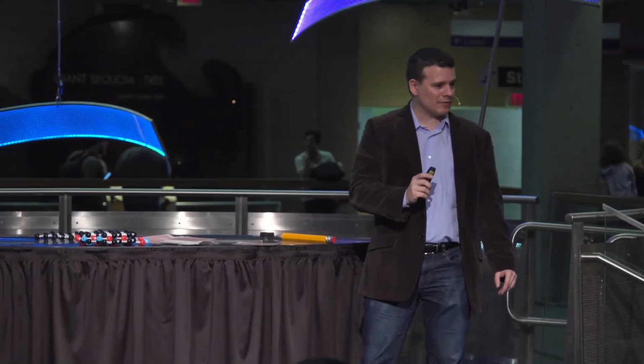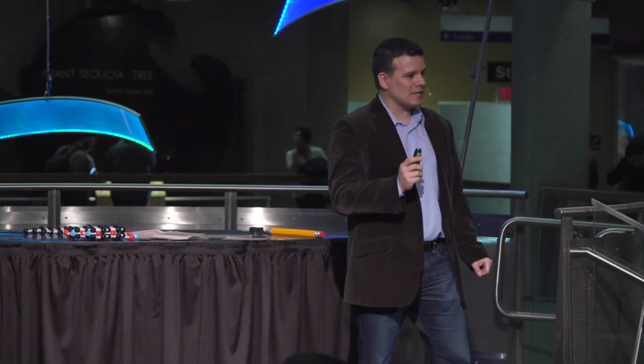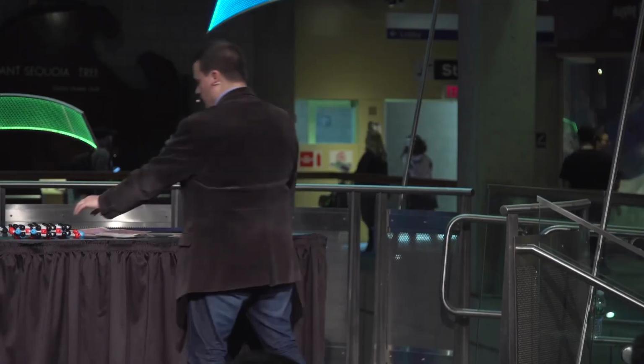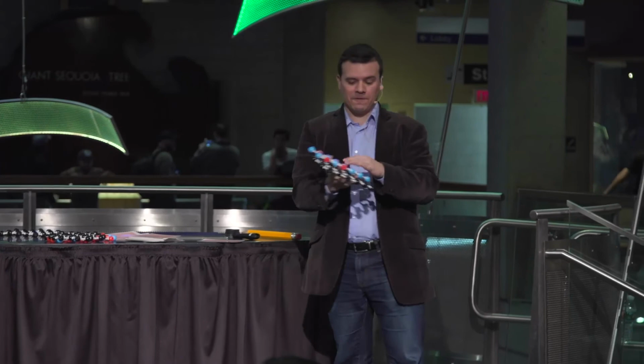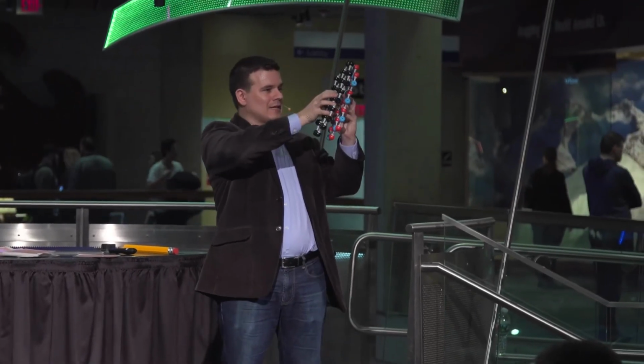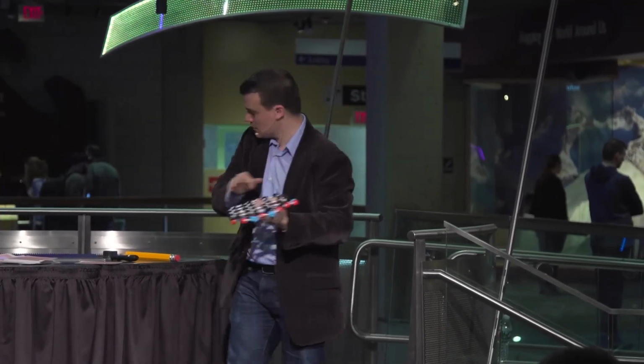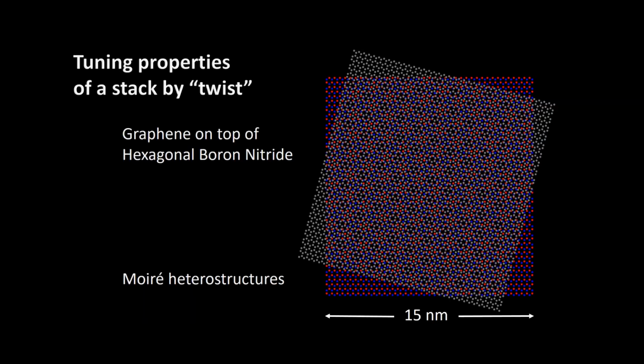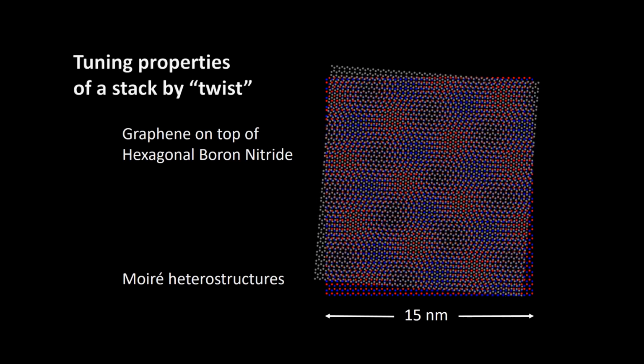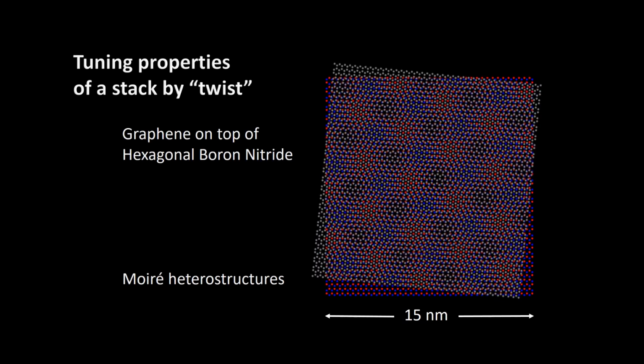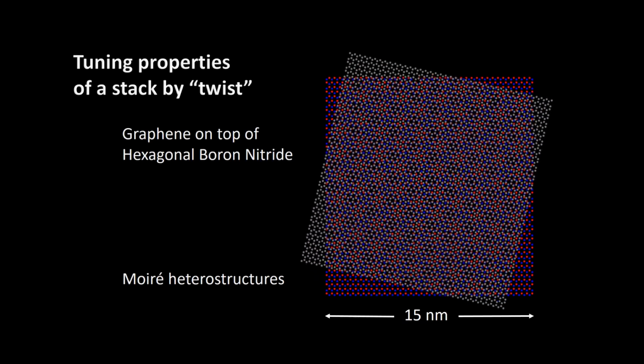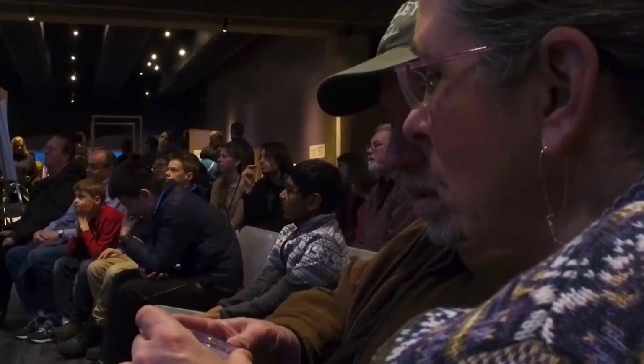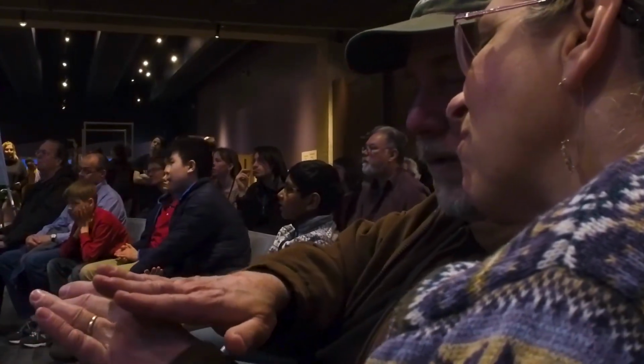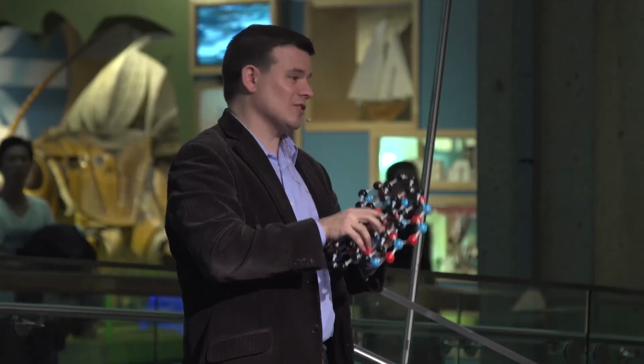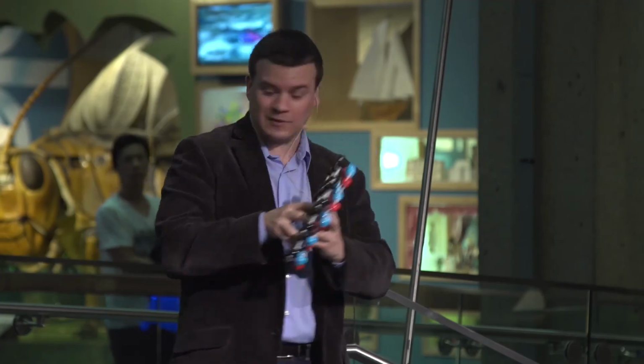The last thing I want to tell you very briefly is the fact that with these materials, you can also rotate these 2 layers. So you can put graphene on top of hexagonal boron nitride and now rotate it like this. You can do something like this. And you see, when you rotate it, you have a pattern that changes, a moire pattern that changes. The properties of the combination of the 2 materials depend on the angle of rotation. So now you can imagine how many of these materials we can make.